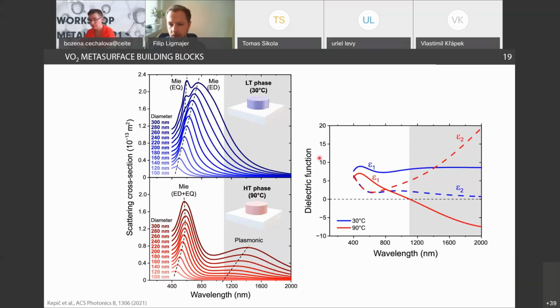The VO2 here is again the dielectric function of VO2, and the stuff I was talking about a couple of slides ago, that in the near and mid IR, the VO2 undergoes this transition from dielectric, that is positive dielectric function, into a metal, so negative dielectric function. However, at visible range, and this was of course very well known, but not many people have used this property, your dielectric constant stays positive all the time, no matter which VO2 state you are talking about.